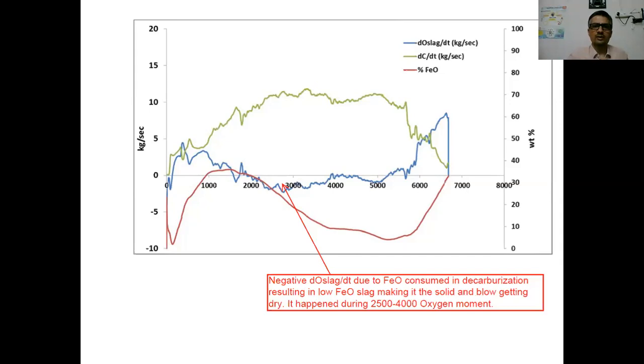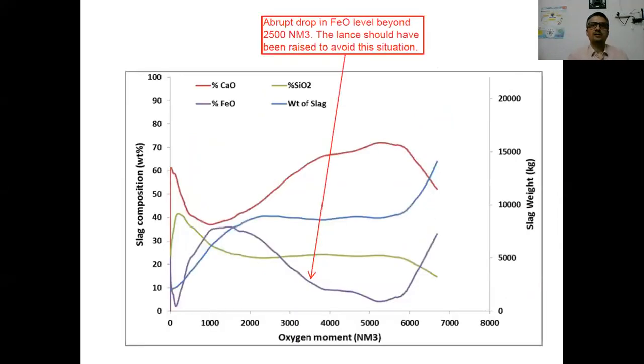So based upon all these calculations, we can predict those happenings well in advance, and the operator can take corrective action by raising the lance height well in advance to take care of those eventualities. Similarly, CaO, FeO, SiO2 are drawn in the same plot. The volume of slag is being predicted. This is the area at this particular moment. The operator is supposed to increase the lance height because it is going below this. So one can look at these plots.